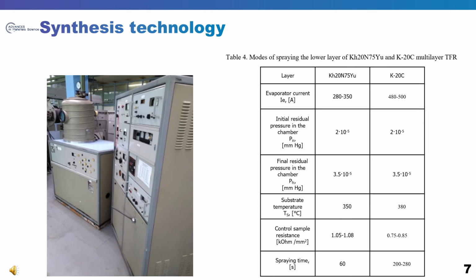The weak link of the nichrome film is its sensitivity to moisture. As a result of exposure, resistive paths are etched due to electrochemical corrosion. To avoid the defects shown, nichrome films are covered with protective films. For freshly deposited thin films based on any materials, a heterogeneous and unstable structure, non-equilibrium concentration of defects and other imperfections are characteristic, which leads to a change in resistance, both over time and under the influence of high temperature due to an increase in structural homogeneity and removal of residual stresses. Therefore, immediately after spraying, thermal stabilization of the resistive layer is carried out in vacuum.